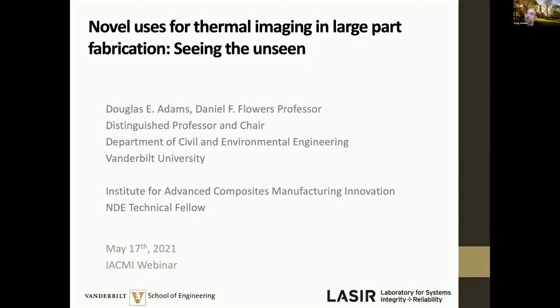But what thermal imaging is looking at is something slightly different. It's looking for a change in the material state. So you could not only see voids, areas where there's a gap that would change the nature of the heat transfer that's occurring, but you could also see, for instance, areas of the material that aren't properly cured, which would lead to a reduction in properties.